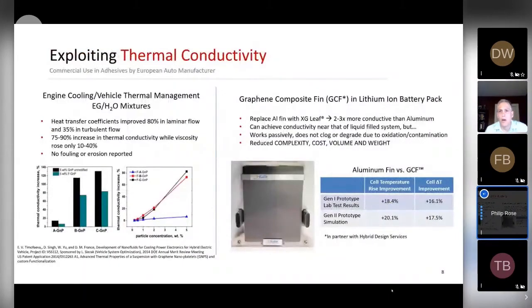So let's switch gears and briefly discuss applications benefiting from the thermal performance of graphene nanoplatelets. I earlier alluded to a commercial application in adhesives, or at least it was shown on our slide. That particular customer didn't want to provide any performance data for this presentation, but I can say that the application is to improve the thermal conductivity in an adhesive used in production by a European auto manufacturer. They experienced failure in the adhesive due to heat, and our customers solved the problem by adding our graphene nanoplatelets to the adhesive, which allowed the heat to be more effectively dissipated so the adhesive no longer failed.